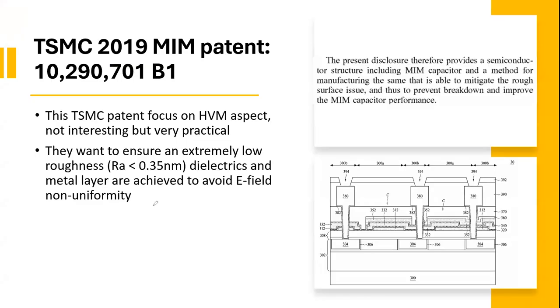For example, this paper is interesting. They want to do the MIM capacitance, and they come up with a patent, and the patent says that they focus on the HVM aspect. They're not doing the novelty of this patent; the compounds they have ensure extremely low roughness. The Ra is less than 0.35 nanometer for dielectrics to avoid E-field non-uniformity. Imagine if your metal or dielectric is non-uniform, you of course create local E-field non-uniformity, and anything non-uniform will give you more noise. So this patent is geared to reduce the noise, making it very smooth. That's interesting to me.